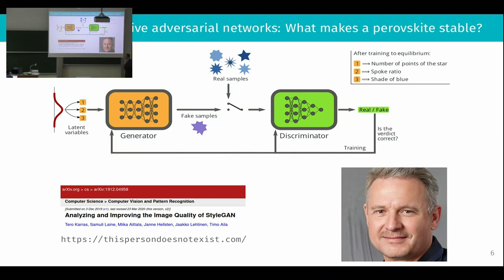On the surface, this is just a classification problem, so nothing special from the point of view of machine learning, but it's a problem where we have very few training data in the context of the enormous quantity of possible configurations. A class of models that's been shown to work very well in this context are generative adversarial models, pioneered by the gentleman you see here, Ian Goodfellow. So a generative adversarial model is actually composed of two neural networks, the generator and the discriminator. Here the discriminator is the actual classifier. It's supposed to take an oxide structure, adopting now the language of our particular problem, and return true or false, real or fake, depending on whether it belongs to that category we are looking for or not. On the other hand, the generator trains to be better and better and as good as possible at fooling the discriminator into thinking the structures it's making up are actually real.